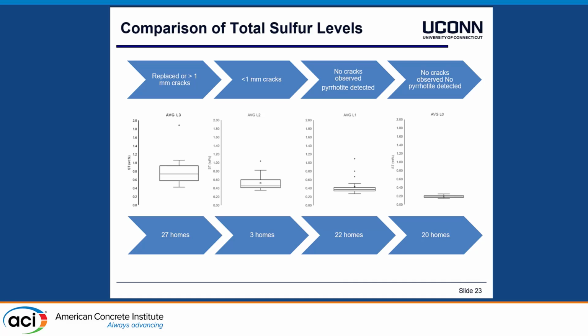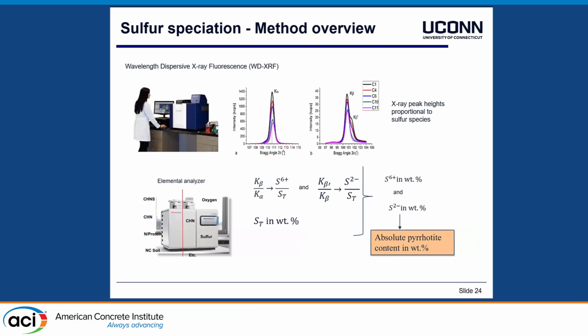For example, foundation has been replaced or they show cracks more than 1 millimeter, then the total sulfur works out to, for example, the average here with the standard variation, or if the foundation was not replaced, smaller than 1 millimeter, then the total sulfur currently measured is this, and so on, or no cracking observed, pyrrhotite detected is here. So it gives you a sense of where there would be a critical limit for reaching a deterioration which needs replacement of their houses. So this is being done, is continued to being done, and it needs to be done over the next years as well, because it's a time-consuming process to get those samples and analyze them in the lab.